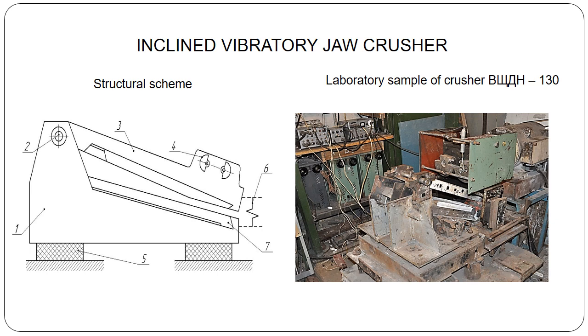Grinding was carried out on a laboratory sample of a vibratory jaw crusher, which includes a passive, lower crushing jaw 1 and an active jaw 3. Vibrations of the jaws are generated by a two-shaft inertial vibration exciter 4. The destruction of the material occurs in the crushing chamber formed by the working surfaces of the passive jaw 1 and active jaw 3. Crushing was carried out on bottles with a cylinder diameter of 90 millimeters,